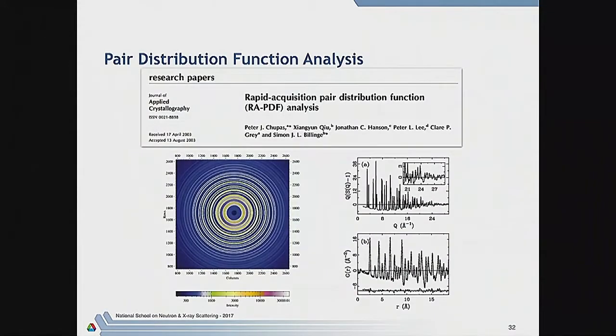And here, of course, you can do PDF on instruments like Nomad. At the APS, I don't know if any of you saw this beamline. Peter Chupas and Karina Chapman run a beamline, which is 11-ID-B, where they have an area detector, and which means that they measure the pair distribution function in single measurements, and it's very fast, and it's heavily oversubscribed. And one of the powers of the technique is it allows you to look at in situ studies. You can scan across, for instance, an actual electrochemical cell and see the variations in the disorder as you go across the cell. So we can't mimic that with 3D PDF, for reasons I'll come to,